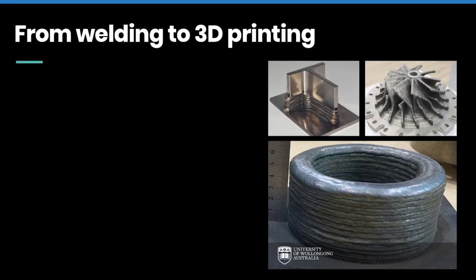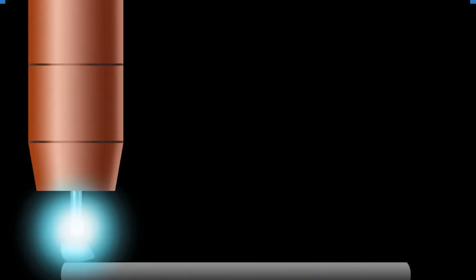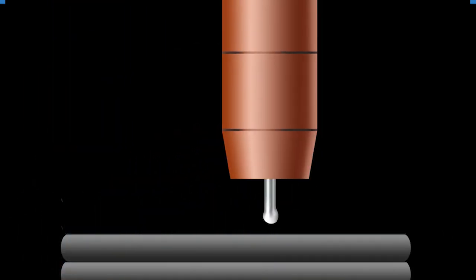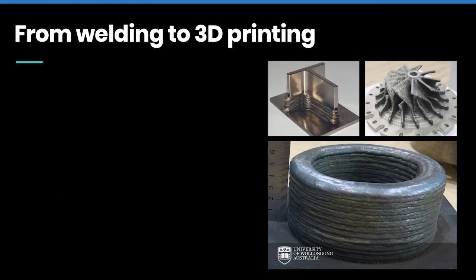After finding out that the weld metal microstructure offers better molten salt corrosion resistance and also higher strength when compared to the parent metal microstructure, we have decided to team up with our colleagues from University of Wollongong and use their 3D printing technique based on the well-established welding technology to 3D print a test component which would have desired weld-like microstructure. We are currently in the process of examining the strength and molten salt corrosion performance of this component, but we believe that this development will accelerate adoption of molten salt-based energy generation and energy storage systems and thus contribute to the faster decarbonization of the power generation in Australia.